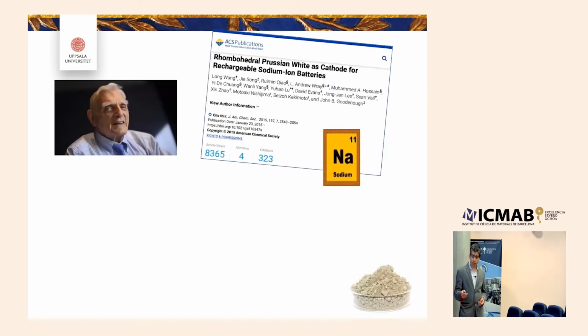Then we happened to see this paper by John Goodenough on Prussian white, which looked excellent because it showed two flat plateaus, relatively high capacity of 170 milliamp hours per gram, with two flat plateaus, meaning we could use it as a counter electrode. That was the main idea in the beginning.